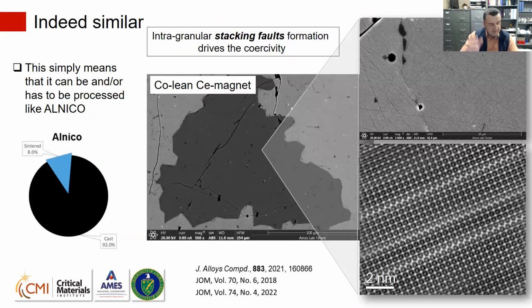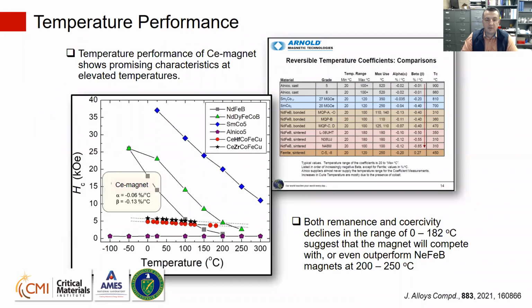But if this is similar to ALNICO, then the temperature performance has to be similar to ALNICO. And indeed, when we measure temperature performance of coercivity versus temperature, we see that it's almost parallel to the ALNICO line. So very different to other permanent magnets. Okay, that's very encouraging,